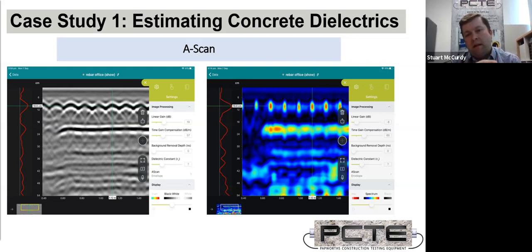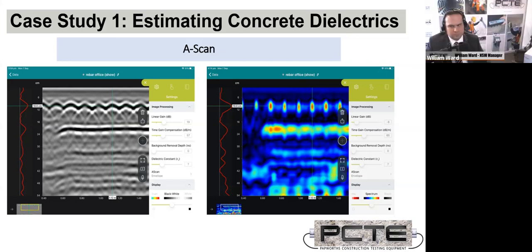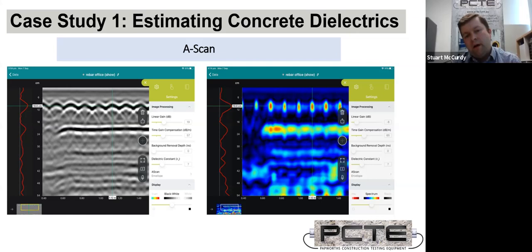We can bring up an A scan. We just basically slide our finger over and we get the A scan view. And where we have a peak is where we've changed from concrete to steel. So what I'll do is just move that crosshair so it's on the peak of the A scan, and I know I'm at that change from concrete to steel. I'm still using a dielectric of 7, but I'm picking a better point for where I actually think I've changed materials.